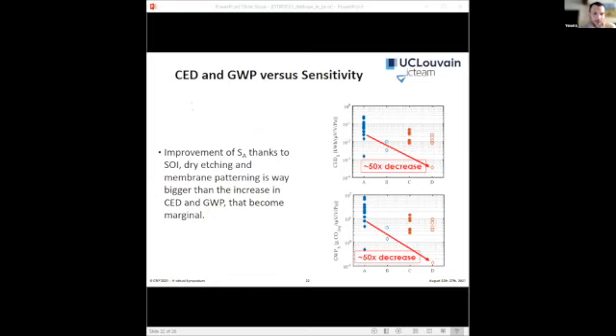Finally, using this last graph coupled with the result of the life cycle analysis, we computed the cumulated energy demand needed and the global warming potential implied per sensitivity units, depending on the technology mix. And we see that the improvement of the mechanical figure of merit thanks to the SOI and the dry etching and the patterning is way bigger than the increase in cumulated energy demand and the global warming potential per area that become totally marginal.